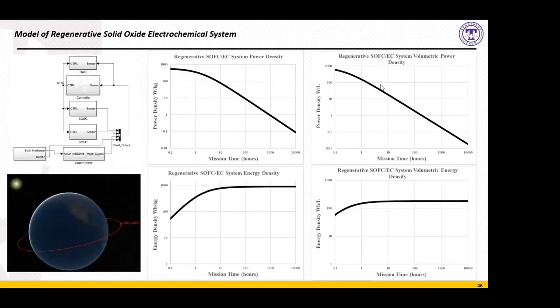So again, we've developed a Simulink model here for the regenerative system and done pretty much the same analysis that we did for the hypergolic system. And we find here the maps of the power density, the specific power density and the volumetric power density, and the specific energy density and volumetric energy density as a function of mission time for a hydrogen-oxygen regenerative fuel cell.